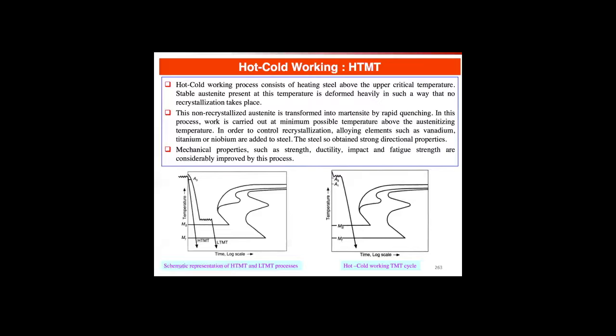When we deform our austenite, we get these long pancake grains, right? So now if we go to martensite, we have anisotropies carried through to our martensite. So now we have a directional dependence to our martensite formation, right? And because we're nucleating at the grain boundaries, we now have a strongly anisotropic martensitic structure in the sheet, and this gives us better ductility, right, and also potentially, depending, improved strength and fatigue strength, right?